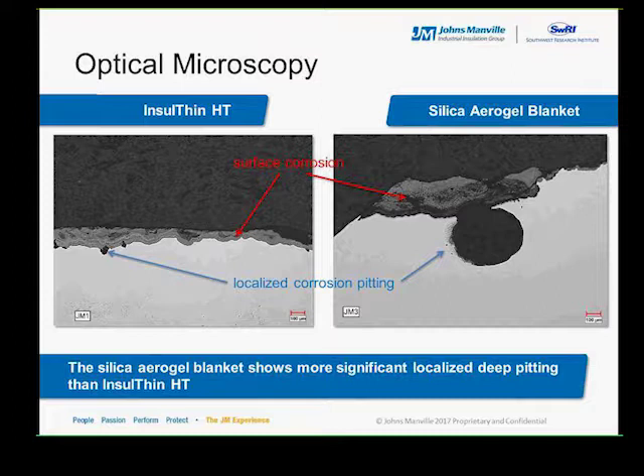SwRI also took some cross-sections and analyzed the pipe samples using optical microscopy. Again, the presence of deep corrosion pits was evident in the silica aerogel blanket more than the Insulthin HT. In the microscopy images on the slide, you can see that the dark areas where the blue arrows are pointed show the presence of the pits in the pictures. And though both insulation samples show the presence of corrosion pits of varying depths, the silica aerogel blankets were clearly much deeper and wider than the Insulthin samples at the various points that we looked at. So this is the third piece of data that really confirms that the silica aerogel blanket has deeper pits at the accelerated sweating and cyclic high temperature conditions.